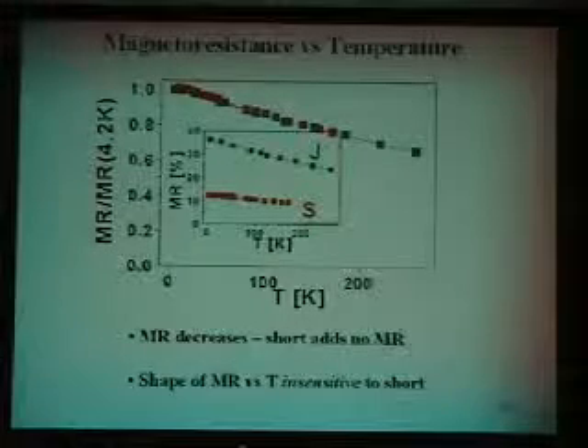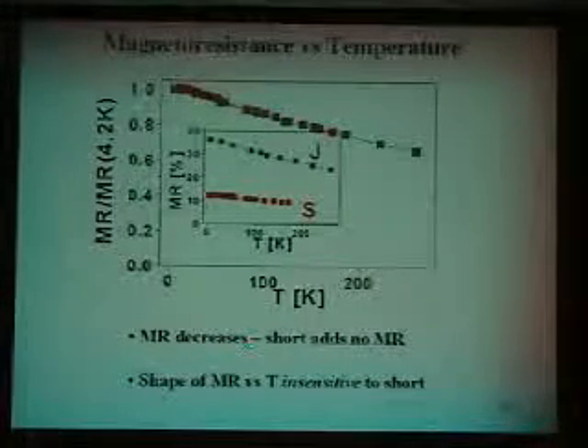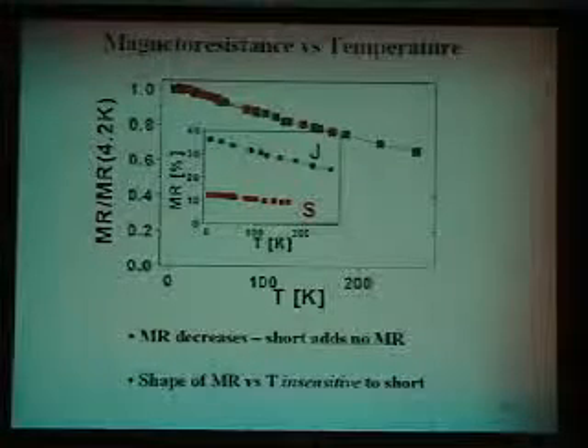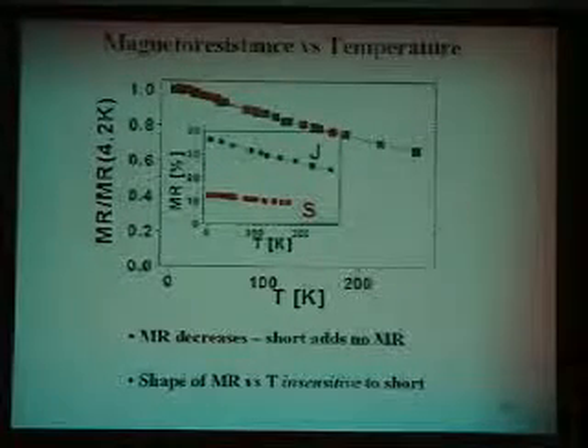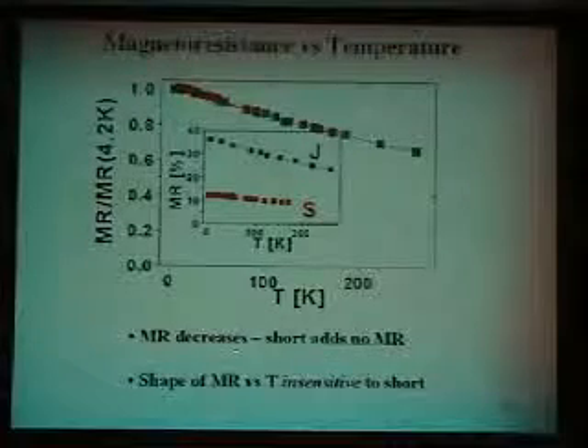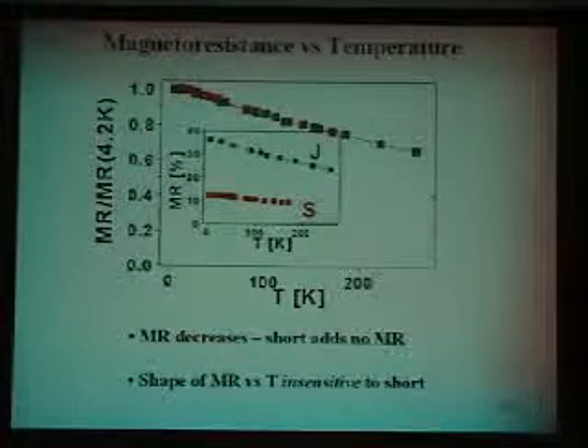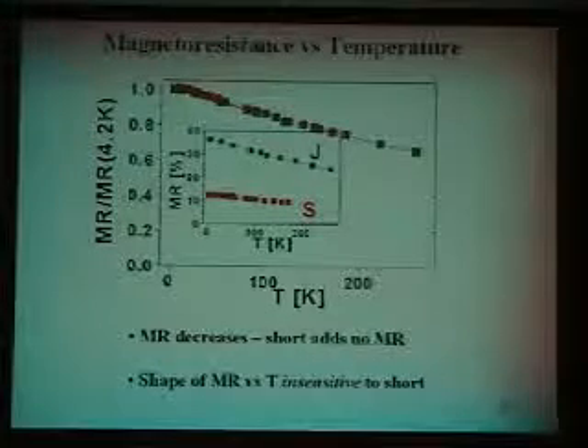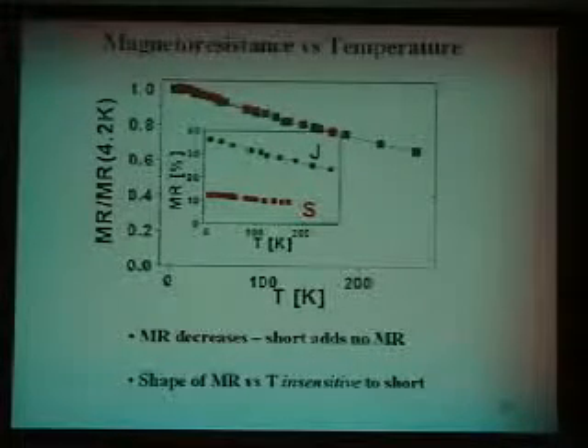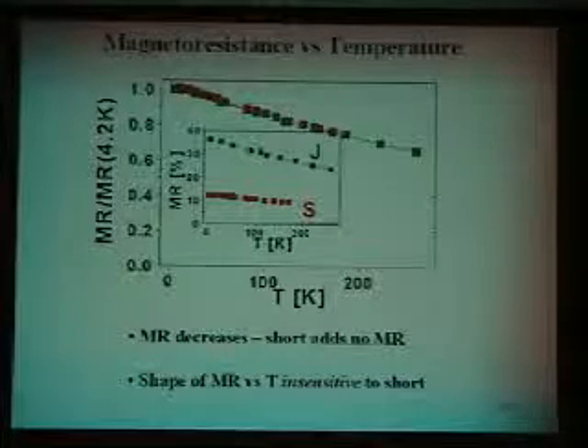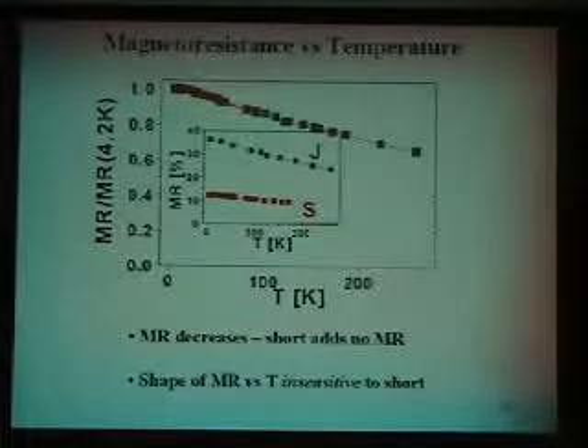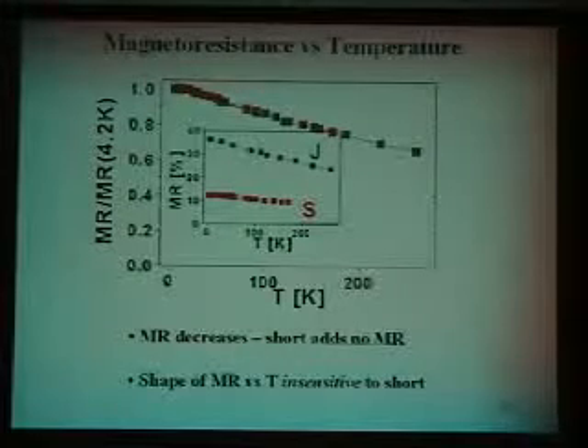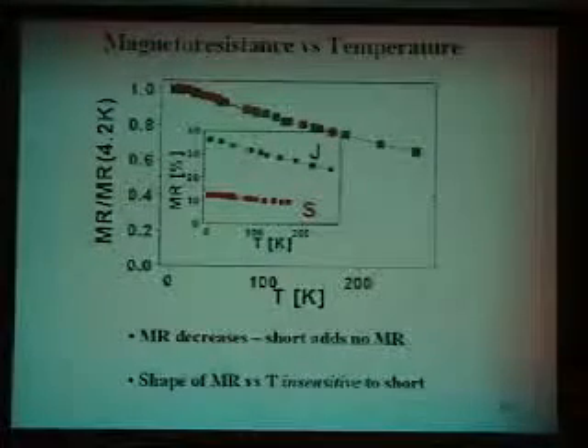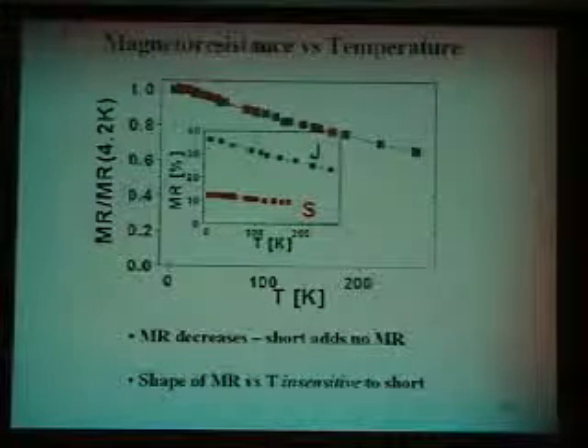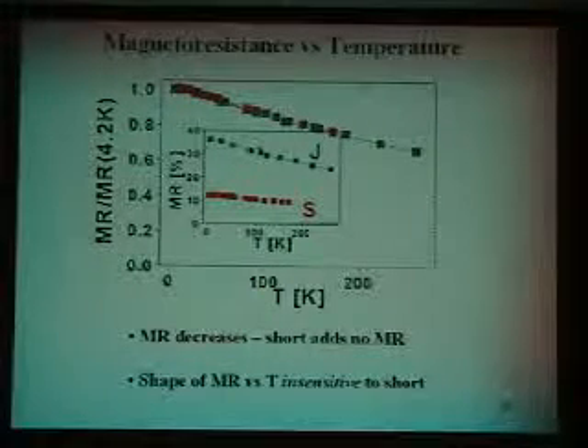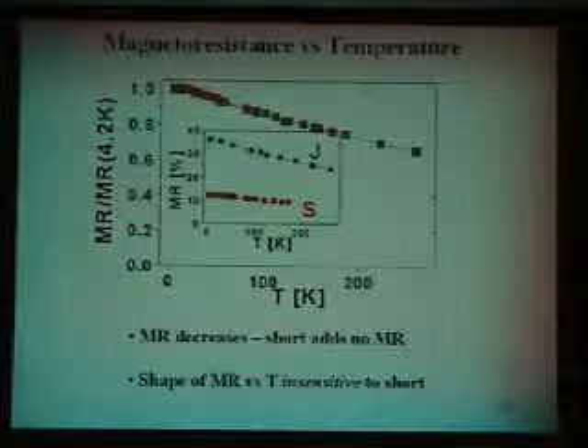If you look at the magnetoresistance, it decreases, but the shorts have no magnetoresistance. So if you make shorts, you zap this junction, and you look at the magnetoresistance, there is no additional magnetoresistance added to this. As if this ballistic magnetoresistance, God knows where it comes from, is not related to this one. It doesn't appear here. Now, this data that I'm showing you was invoked by the ballistic magnetoresistance guys as support for their theory of what's going on there. I'm saying the opposite. I'm saying there is no additional magnetoresistance added here by the shorts.